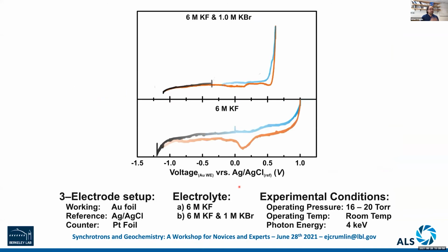So just an example of how to contextualize this, visualize what's happening. What I want to show you is how we can really apply this technique. So the main thing I want you to take away from this is an electrochemical cyclic voltammetry plot. What essentially this means is we're changing the voltage and current, and we're trying to drive a reaction. As we change the electrolyte to potassium fluoride, let's just say for the most part, nothing chemically is happening. But when we add bromide to the system, we see a very strong current. So that means something is being promoted at a much lower potential. So let's look at the differences between these two.